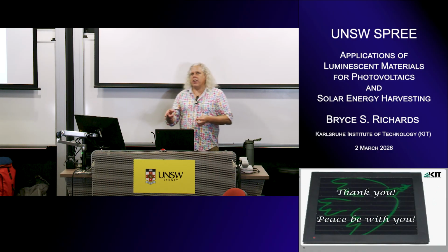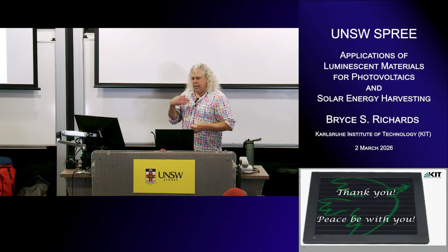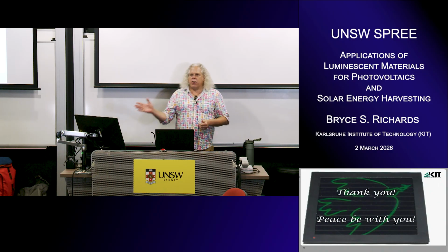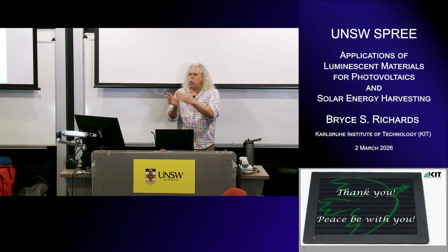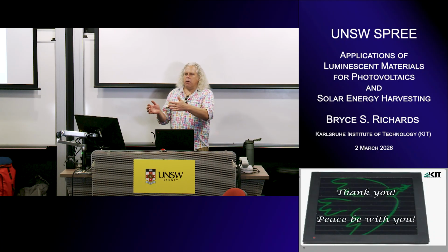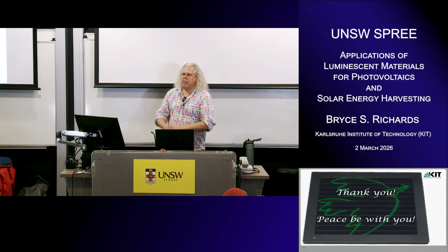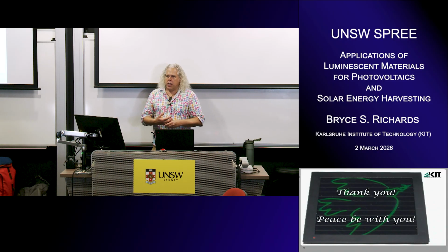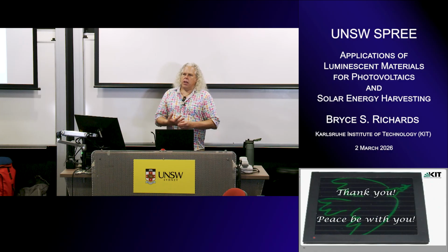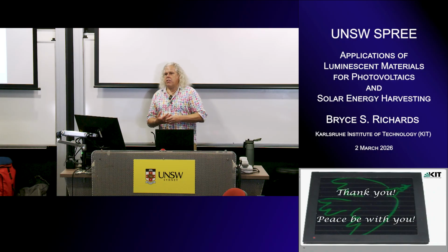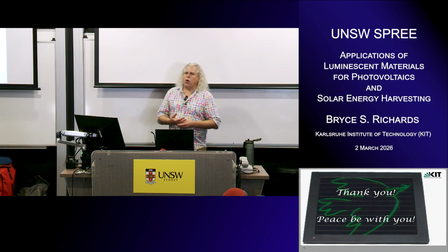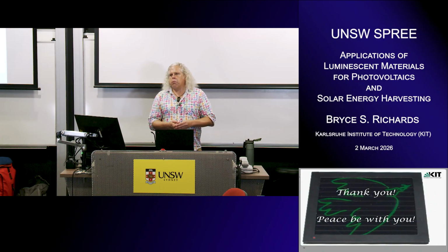I think the difference here is that there's probably a trade-off in the amount of ytterbium you introduce. You probably want quite a bit because it's your emitter, but every time you introduce an ytterbium ion, you also introduce at least a defect. I'm not the expert here, and I suspect this is what's happening. I haven't looked into the photophysics of this yet. There is a concentration quenching, I believe. The concentration quenching is known, so people suspect that 20% ytterbium is the optimum.